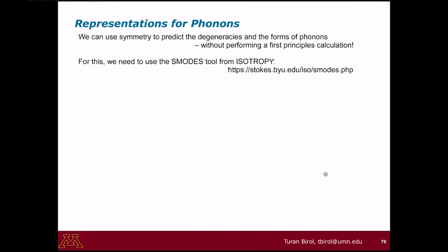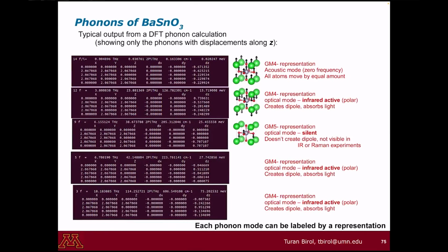Okay. So this already gives us a good bit of information about what experimental observations we may have. For example, if you read an experimental paper and they say they detect 5 different phonon modes that absorb light shone onto them through first order processes, you can already get suspicious, right? Because there's this one mode here, the gamma 5 minus one, that is not supposed to absorb any light.